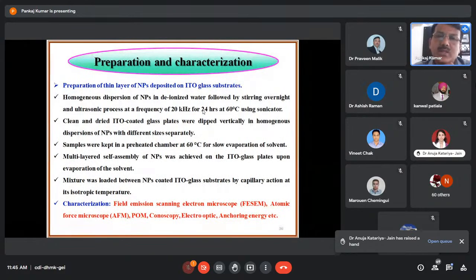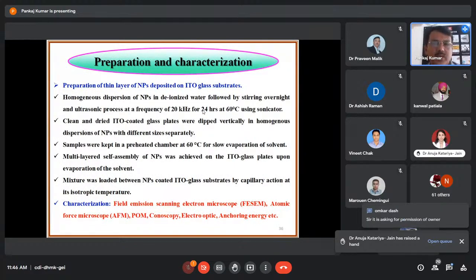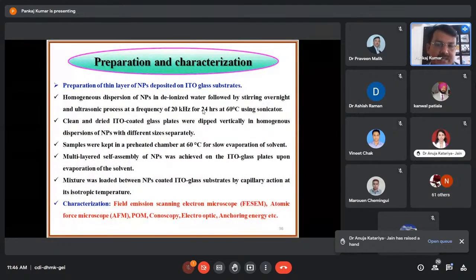So what we have written here means that we just coated the nanoparticles on the ITO substrate, and for this coating the nanoparticles were mixed with deionized water. Before coating, the nanoparticles were well mixed with the help of an ultrasonic process as well as stirring. Then the samples were kept in a preheated chamber at 60 degrees C for slow evaporation of the solvents with the ITO coated glass plates. After slow evaporation, the nanoparticles were deposited on the glass plates, and then the deposited glass plates were used for the liquid crystal display cell. And then liquid crystal materials were filled into the cell made from the nanoparticle coated glass plates.